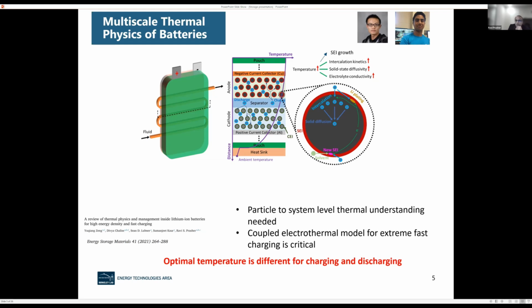You have the cathode. It's not a simple lithium cobalt oxide. It's basically embedded inside. It's like a composite. You have the active material, which is the cobalt oxide material. Then you have a binder which binds it together. Then you have carbon black, which takes the electrons out or in, depending on the charging or discharging, right? And then you have empty pockets where the electrolyte goes in. Same thing happens on the anode side.